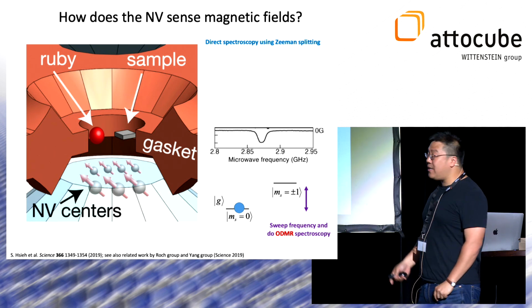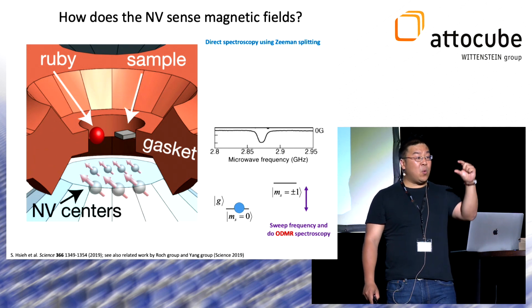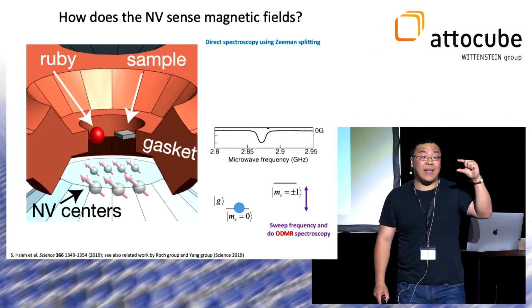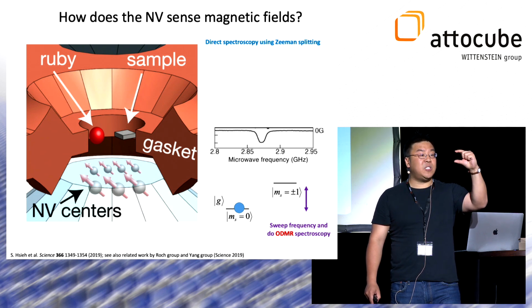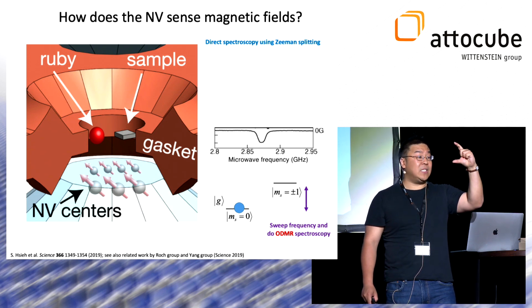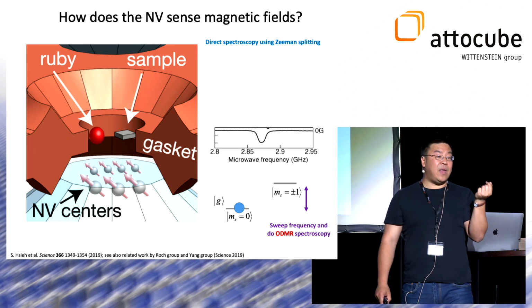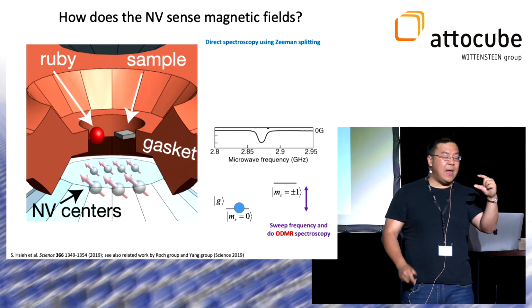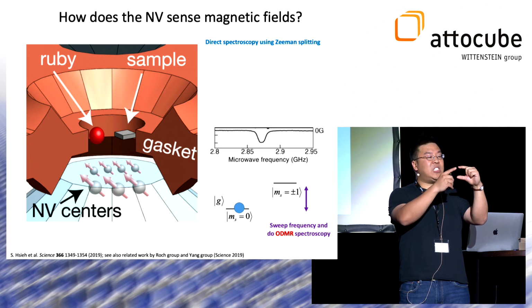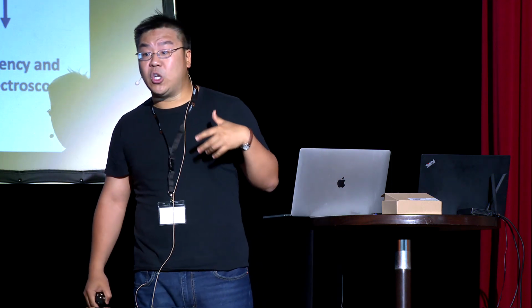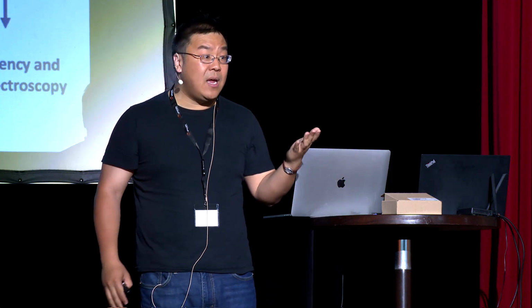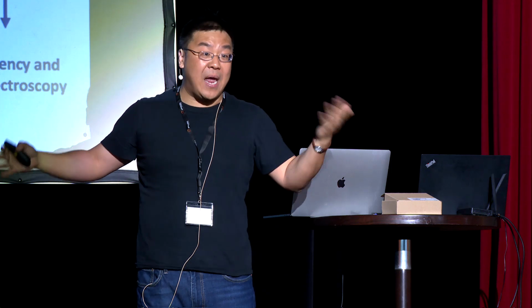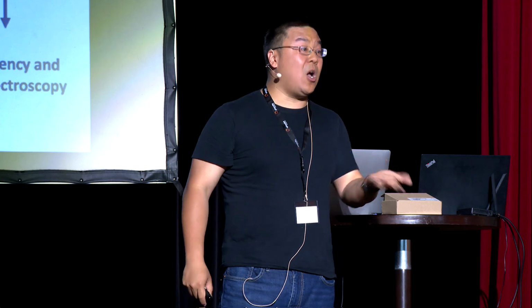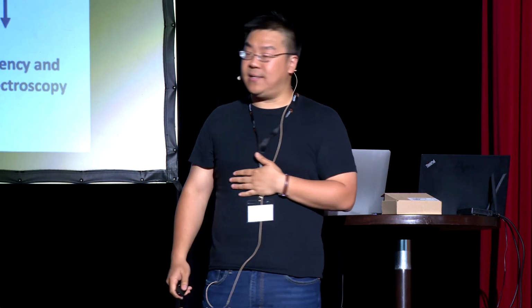In some sense, the signal is just about as simple as you can imagine. If we're interested in DC magnetic fields, we're simply trying to do some spectroscopy of the Zeeman splitting of this magnetic dipole. The lucky thing about the NV center is that the fluorescence of the spin sublevels is different from one another. This allows one to do something called optically detected magnetic resonance. It is just like EPR or NMR, except we detect the signal not using a loop, but rather using optics, just looking at changes in the photoluminescence.